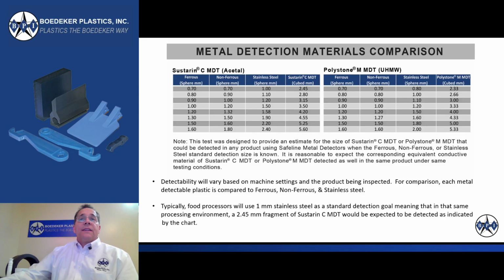First up is the metal detection data. And there's two sets of detection data here based on two different plastics. On the left-hand side, we have metals, and the plastic associated with this test is the Sustarin C MDT, which is a metal detectable acetal. And the data on the right-hand side shows the metals and in association with the Polystone M MDT, which is a metal detectable ultra-high molecular weight polyethylene. And again, Safeline metal detectors were used.